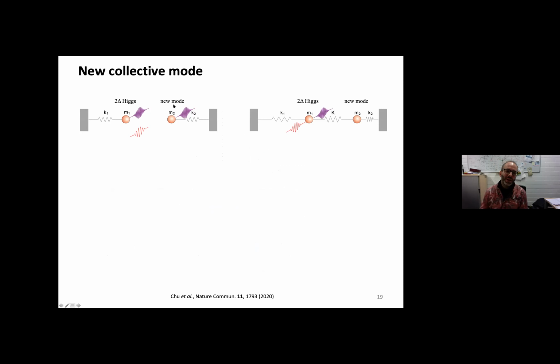So either we have a new mode that is oscillating together with this heavily damped 2 delta Higgs mode in our system, or this mode is even coupled to this 2 delta Higgs mode in the system. The question is, how can we figure out what is the difference? So we can use this independent oscillator model, and then we can model this in a way that we mimic our experimental data. But for this, we would have phases that would go from low to high, both for the heavily damped 2 delta Higgs, which has basically a very broad phase jump, and the new mode that would be underdamped, that would give a sharp phase jump, but from low to high.